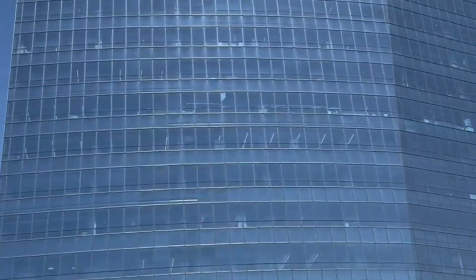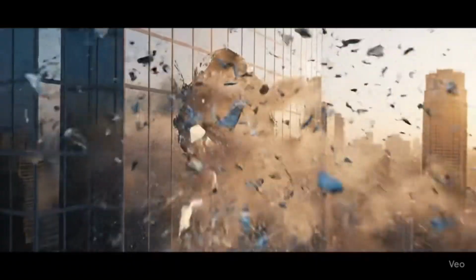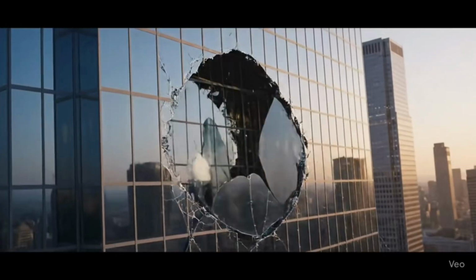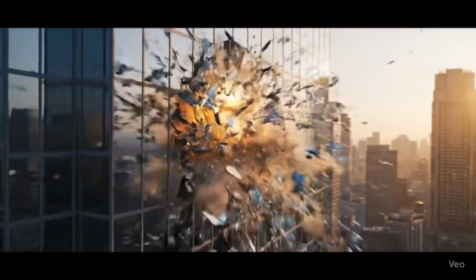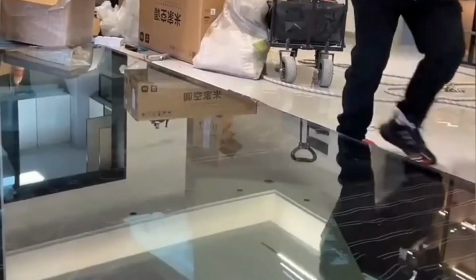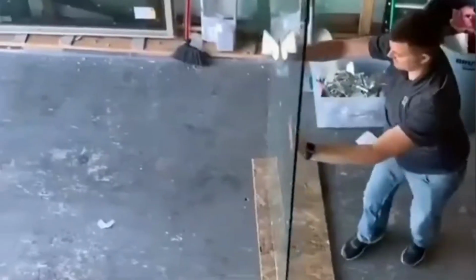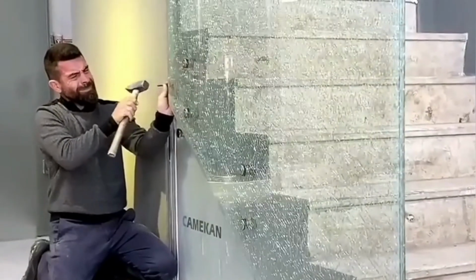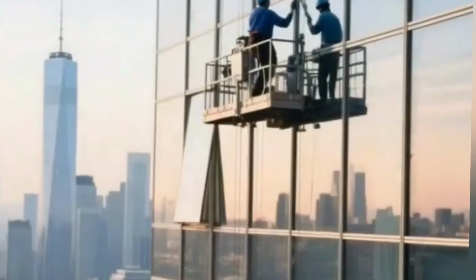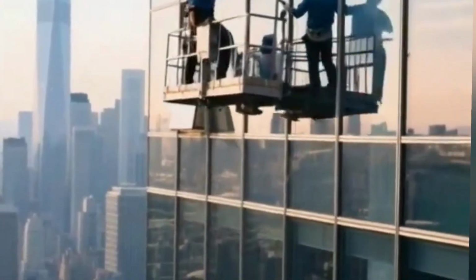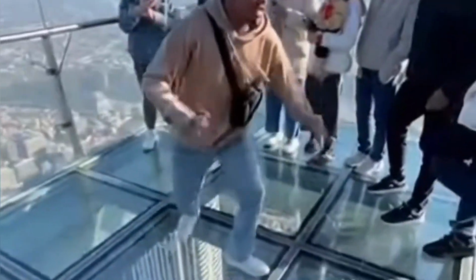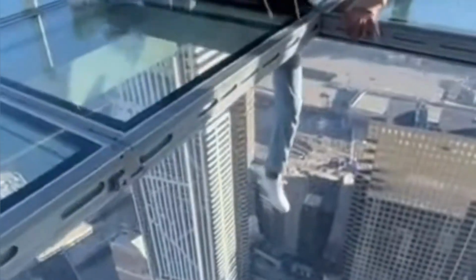The most infamous culprit is something you can't see with the naked eye: nickel sulfide inclusions, or NIS stones. During the float glass manufacturing process, tiny particles of nickel and sulfur can become trapped in the glass. In annealed or heat-strengthened glass, these inclusions are harmless, but in tempered glass, which is rapidly heated and then quenched to create surface compression, the story changes dramatically. The rapid cooling traps these NIS particles in a compressed state. Over time, perhaps years later, they slowly expand back to their original size.